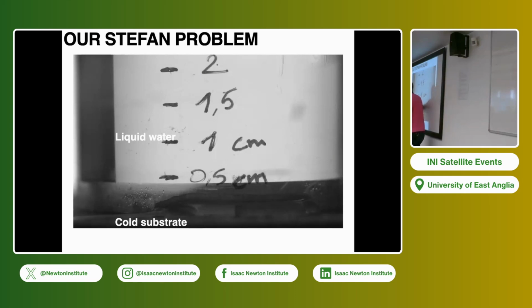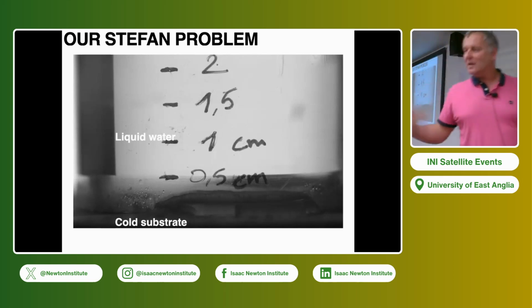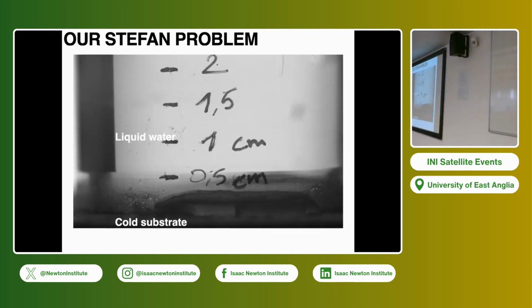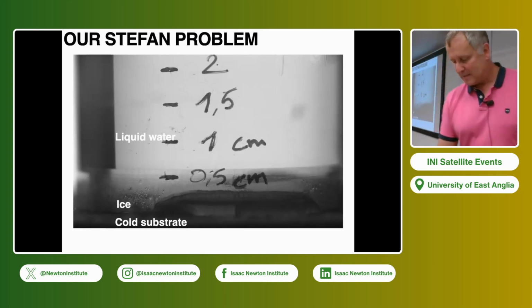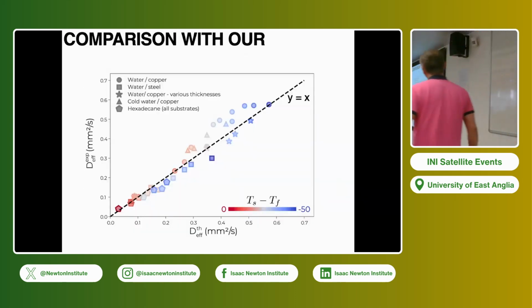Basically, you can measure how this layer of ice is growing, and you can fit it by a square root of time. Then you can get experimentally this D effective, this diffusion coefficient, from experiments, and compare it with the one from the theory, and you have a very good agreement. So this is the experimental measurement, and this is the theoretical one.